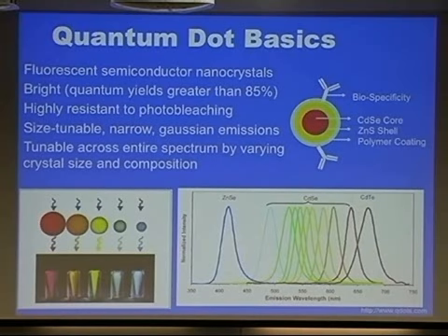as we go through this graph. This is 400 nanometers. The lines are color-coded here. 400 nanometers is blue light, and then you go through just like a rainbow to green, aqua, green, yellow, and red. 700 nanometers is red light. And I want you to remember this graph: from 400 to 700 nanometers, if you make these different sizes of nanocrystals, they emit distinct colors. They emit very narrow spectra that are distinct colors. So hit the next slide.